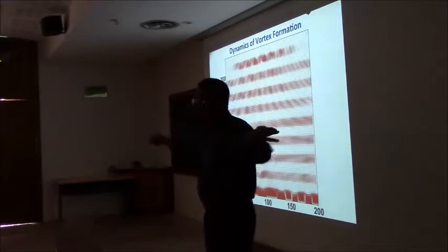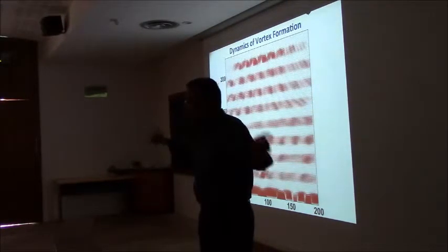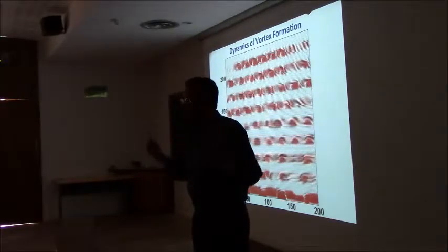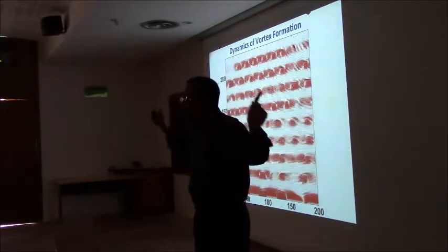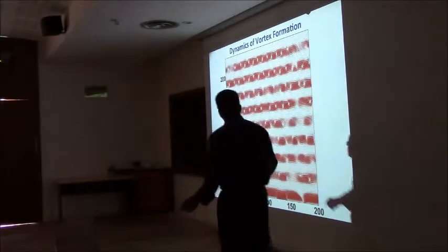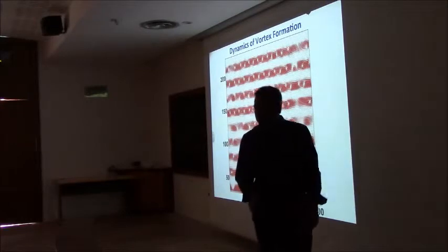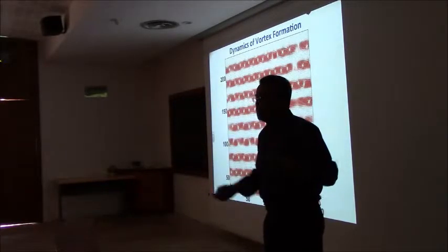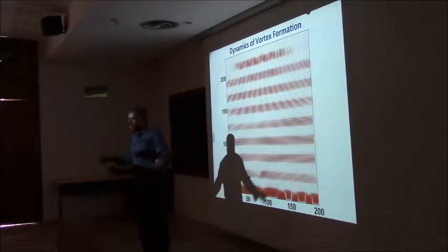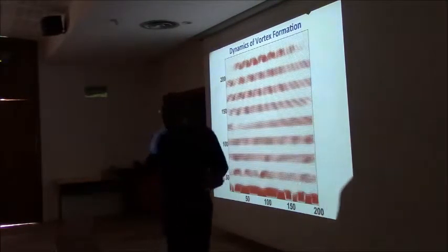Dipole fields, which are very electronic in nature, say, hey, look, you're giving me 100 microcoulombs per centimeter squared, approximately 80 for the real number, and it says, put the polarization in plane. And so the system, first order, puts the polarization in plane. Okay. But then it says, oh, I have a problem. It's scratching its head, because in putting the polarization in plane, I've also